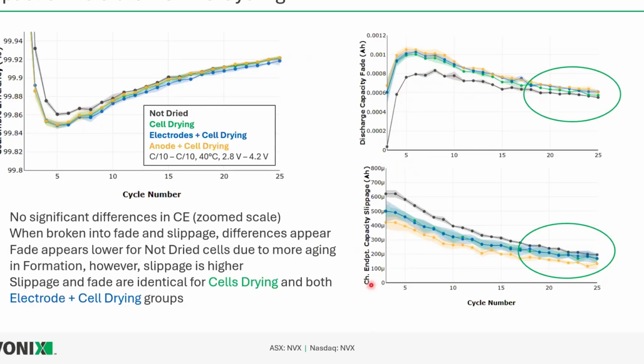And that's because the charge endpoint capacity slippage is higher. There are more of these slippage-based mechanisms happening in this cell due to that moisture exposure. So we can't really let the Coulombic efficiency fool us because there are differences in these different mechanisms happening. And then there's basically no difference between the cell only drying and the drying both electrodes in the cells groups. But again, this anode plus cell drying, so drying the anode and drying the cells once they're assembled, has a lower charge endpoint capacity slippage.